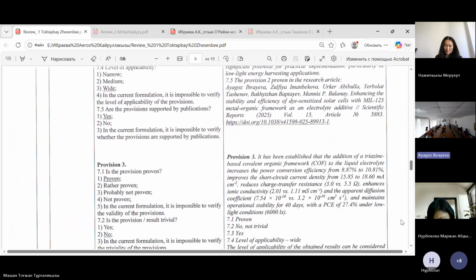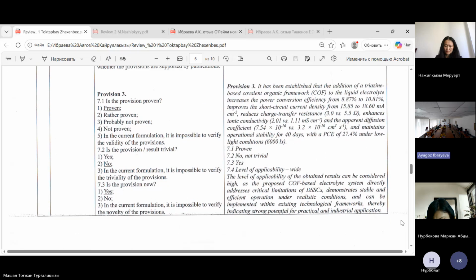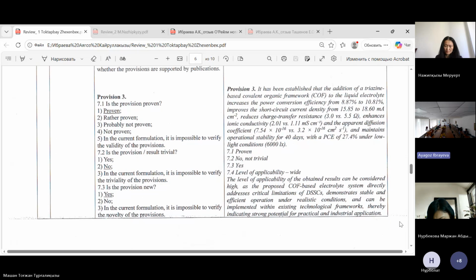And provision 3 is also proven, and it has been established that the addition of triazine-based covalent organic frameworks to the liquid electrolyte increases the power conversion efficiency from 8.87% to 10.81%, improves the short circuit current density, reduces the charge transfer resistance, and enhances ionic conductivity and diffusion coefficient. Based on this provision 3, one paper was also published in Materials Today Energy in 2025.